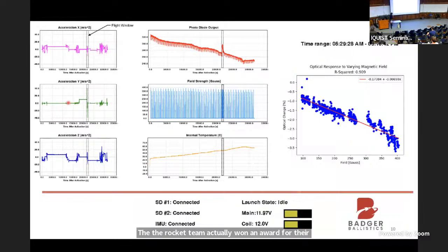But I want to cover a little bit of the data that we were able to collect. We were able to get nice data through the entire operation, all the way from when the team first loaded the rocket onto the launch pad and then waited hours in 100-plus degree weather, and then eventually got launched, and then eventually they recovered it. And the whole time our sensor was working, and we were able to have simultaneous data for the acceleration, so that we know when launch happens. Launch happens at this spike where the acceleration along y, which I guess must be in this vertical direction, goes up to 10 G.